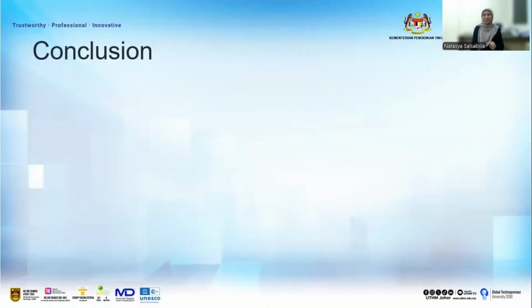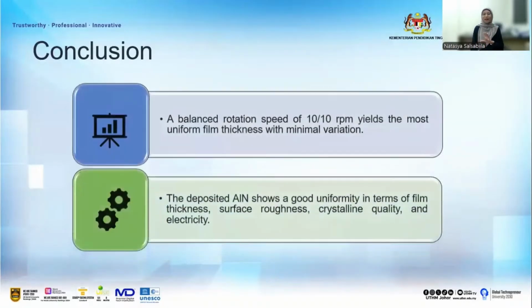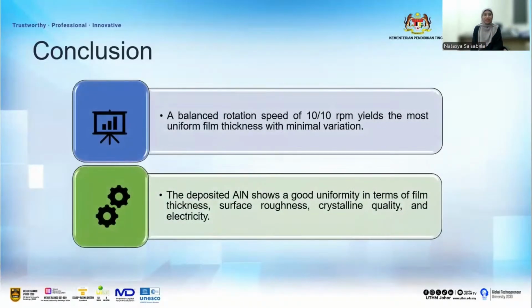Now, we are almost finished. So, to summarize all of this talk, the 10 per 10 RPM rotation setting produces the most uniform and highest quality AlN film. Then, the uniformity study shows that the AlN film has consistent film properties across the wafer, and it's very promising to proceed with further device fabrication.